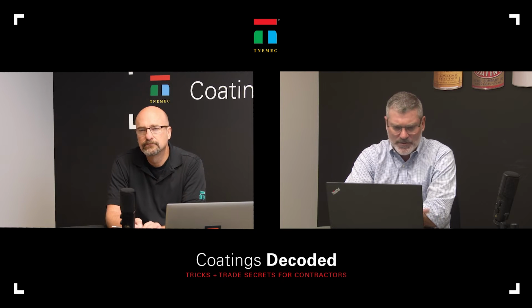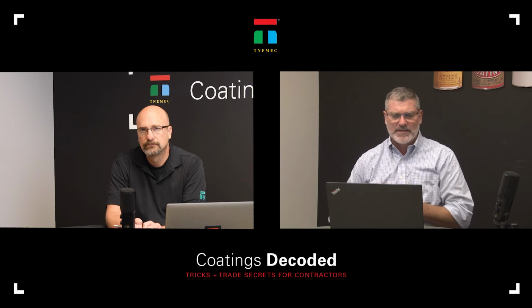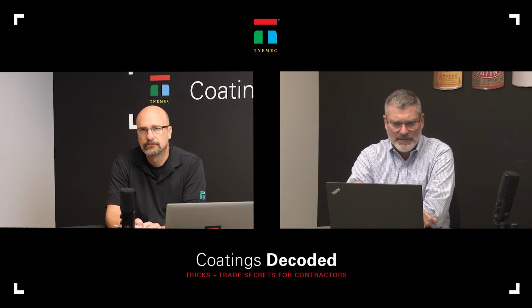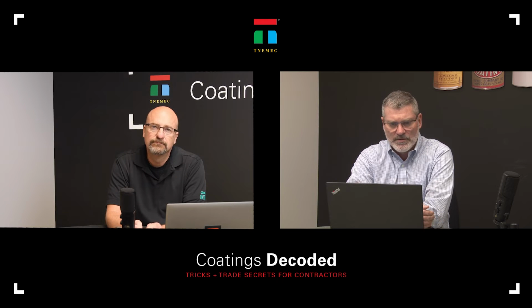Again, we can test for moisture using some ASTM tests. There's a plastic sheet method. There's a relative humidity in situ probe method. There's a calcium chloride method as well. So as long as the moisture content falls within the tolerances of the products, and the design parties and the construction parties all understand the risk of cracking that may occur, then by all means, we can coat prior to that 28 days. When it comes to liquid containing structures, they typically design those in restraint, meaning